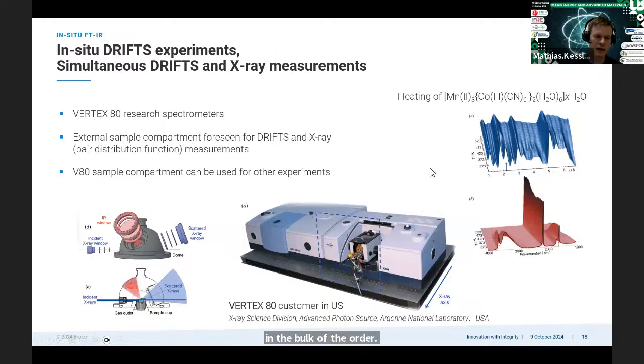We can combine these IR DRIFTS measurements also with additional measurement techniques, for example, with X-ray measurements. So this setup shows you now a special cell where the dome is not only used for two beams of the infrared spectrometer, but also for an X-ray beam, and then the scattered X-ray light is collected. So in this way, we have the possibility to measure simultaneously during the reaction the IR spectrum and with X-ray the pair distribution function.